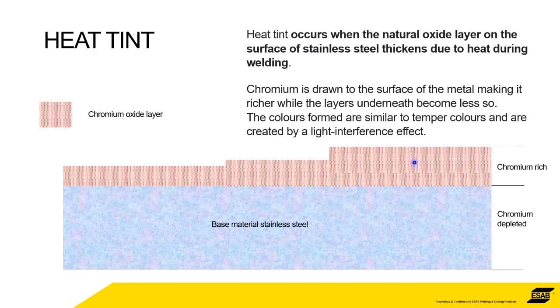So if you have an excess of chrome, chromium-rich layers, because of the heat tint and the excessive heat tint, the darker the heat tint, the thicker the layers, the base metal immediately underneath that is depleted of chrome by definition. The chrome has to come from somewhere, so it comes from the base metal. So in order to restore the properties of the stainless steel, not only do you have to get rid of this chromium-rich heat tint, but you also have to get rid of the chromium depleted layer underneath. And again, we're not talking millimeters thick, we're talking microns. But you have to get rid of that chromium depleted layer underneath, because that's vulnerable. That doesn't have the same corrosion resistance as the proper grade of base material stainless steel.